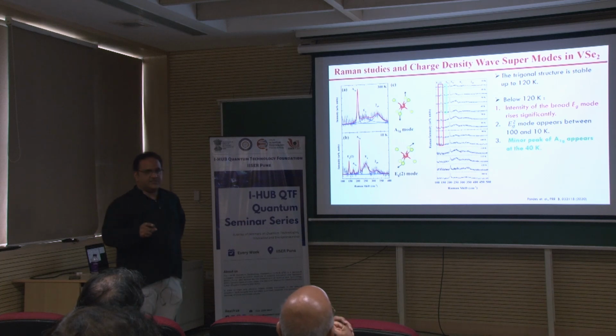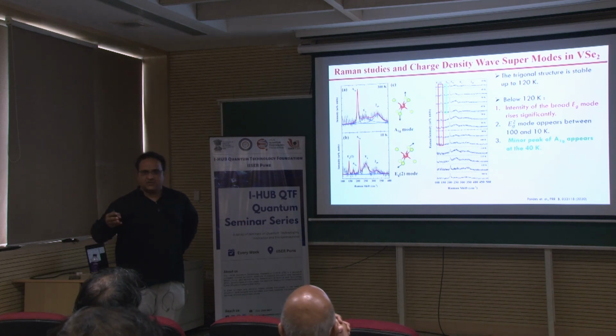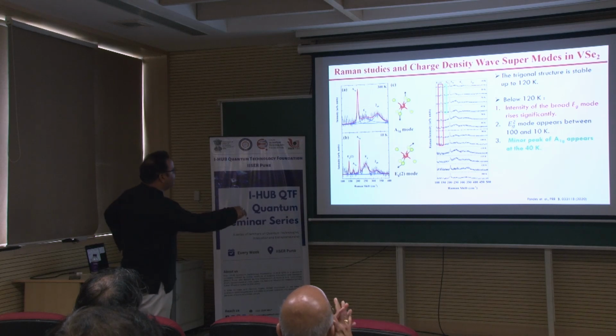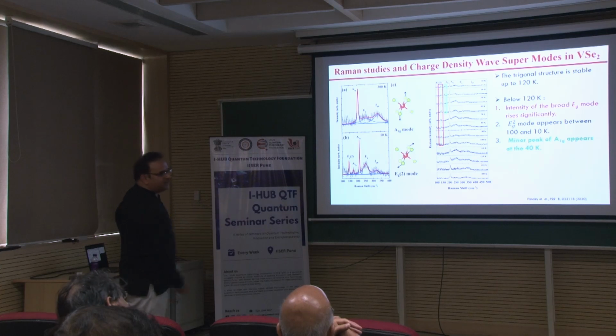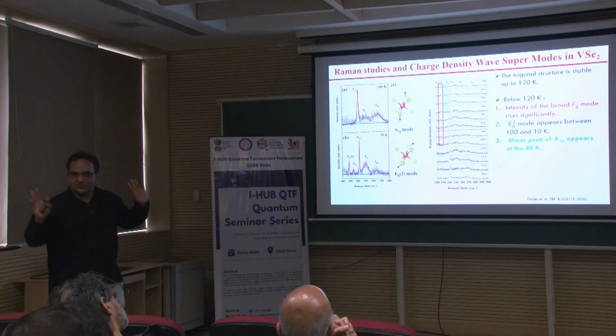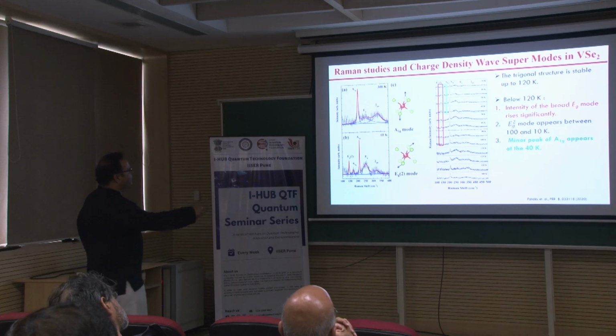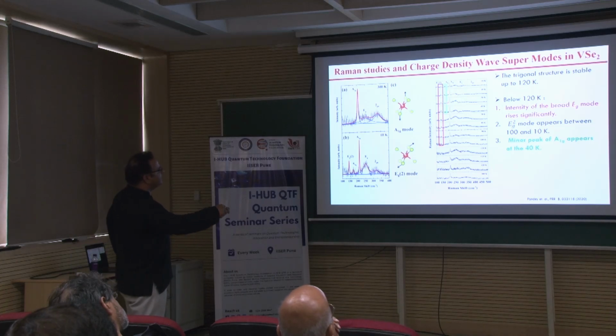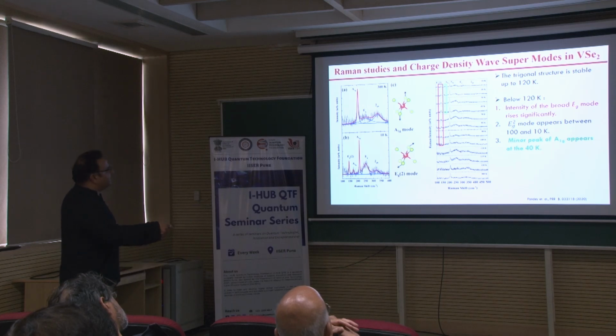The charge density wave transition for VSe2 is around 105 Kelvin or something. If you go below 100 Kelvin, there is nothing here, but if you go down until 40 Kelvin, you have something happening here which goes up. So you have these modes which come up only in the charge density wave, certain modes which come up in the commensurate charge density wave state. There are 2 new modes coming up. One is coming because of the incommensurate region, and another one because of another ordering here. And the intensity of the Eg mode rises very significantly.